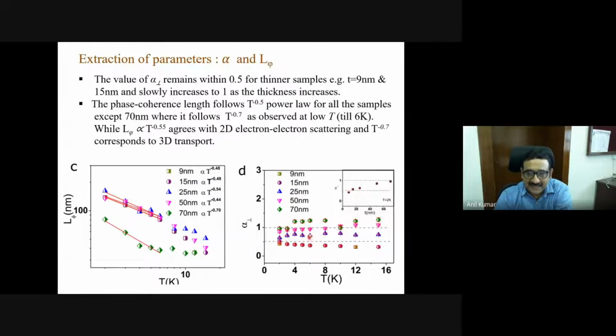As you decrease the thickness to very low thicknesses like 9 nanometers, 15 nanometers, my top surface state and the bottom surface state start coupling to each other, and I get alpha equal to 1, alpha equal to half. That tells me it's a single conducting channel. Similarly, the conduction mechanism also varies as the thickness of this material changes.